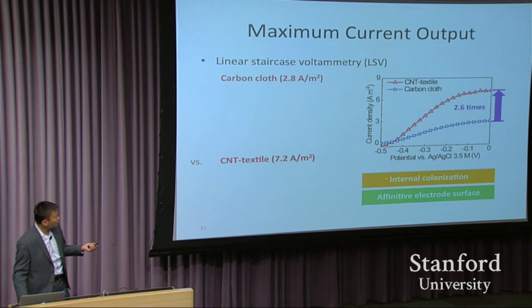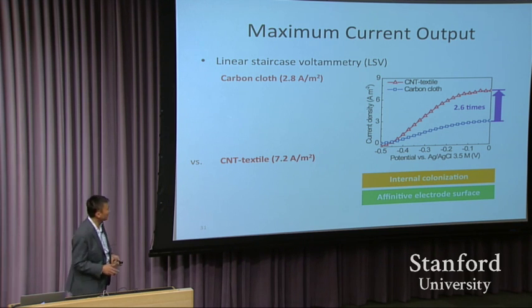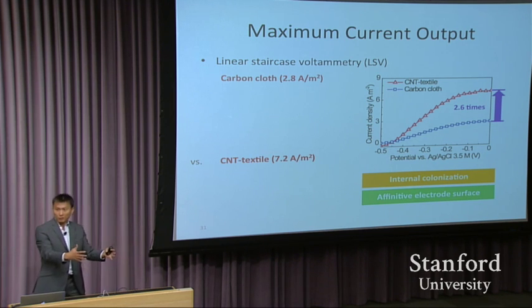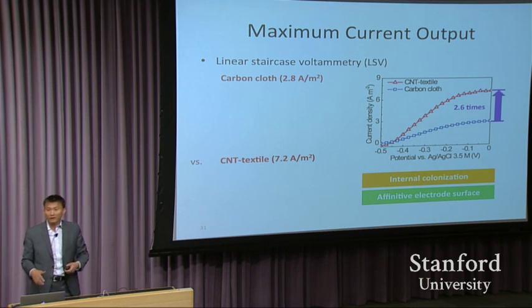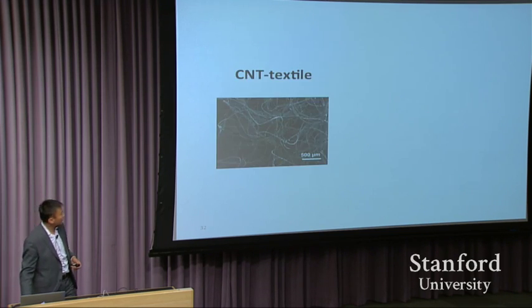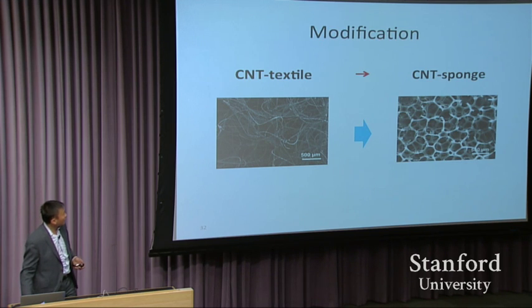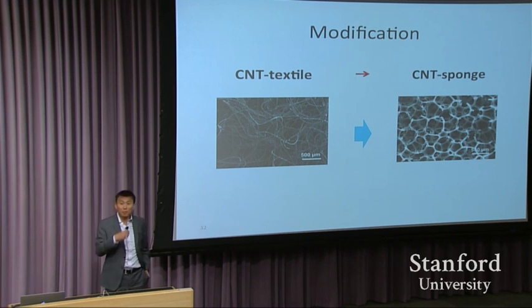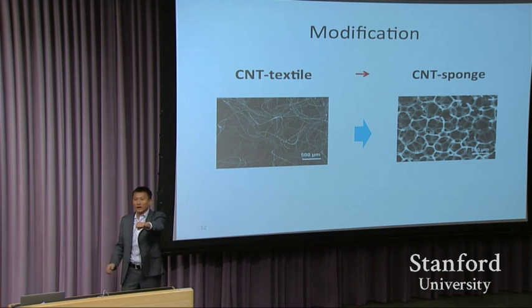So this is due to so-called internal colonization. Microbes can go inside of the electrode through these big pores, and the strong affinity of the microbe with the electrode surface. And then if you compare, look at this, and then we were searching for better porous structure. And the first time we did it was on a textile. But textile has a problem. You see each of these fibers, one fiber going this way, the other fiber going that way. So what about the crossing point?